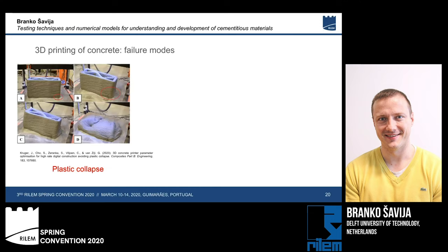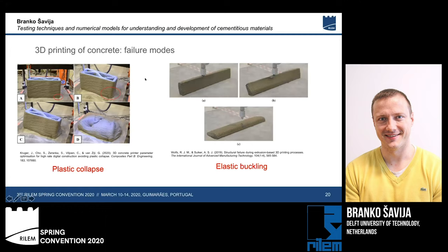The first failure mode that is interesting and important is the so-called plastic collapse. The material is, during this process, still in a relatively fresh state. It does not have a lot of strength. And if we add a lot of layers on top of it, the material cannot hold this and can collapse due to the load. And we call this plastic collapse. This is one of the main reasons that 3D prints fail. Another reason is the so-called elastic buckling, where the complete structure can overturn due to geometry nonlinearity occurring in the